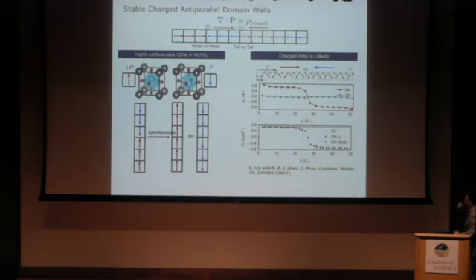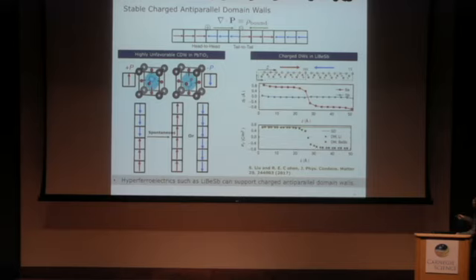So this is a supercell. It has one head-to-head domain wall in the middle of the supercell and a tail-to-tail domain wall at the boundary. What I show here is the atomic displacements and also the polarization across the supercell. As you can see, it clearly has these well-defined anti-parallel 180-degree charged domain walls. So this really comes from hyperferroelectricity, the persistent polarization in the presence of very strong depolarization field. What's surprising is if you look at the polarization in this bulk-like region away from the head-to-head domain wall, you can see the polarization value is very close to the single domain value.